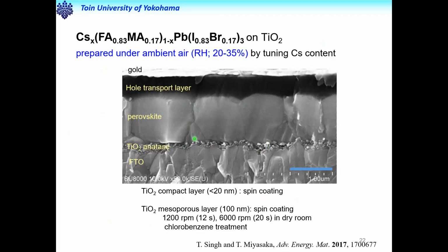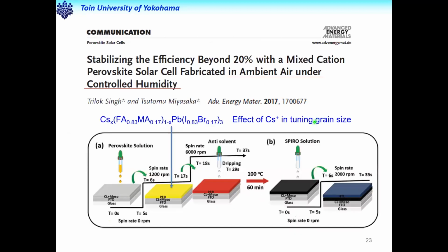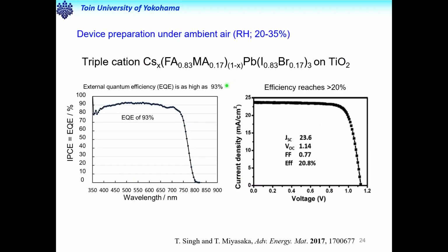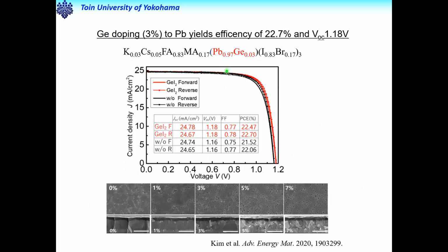So we have been making an effort to make a smooth, large-grain perovskite layer to enhance the efficiency. Also, for cost reduction, we hope to create an ambient air process without using vacuum or a dry room. So we could achieve efficiency beyond 20% with these materials. And recently, we tried to dope germanium into lead to improve the quality of the crystalline. So this is one of our champion efficiencies of a single cell, 22.7%, with an output voltage of 1.18 volts.